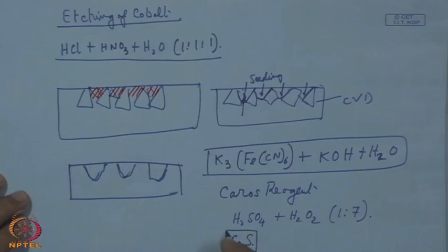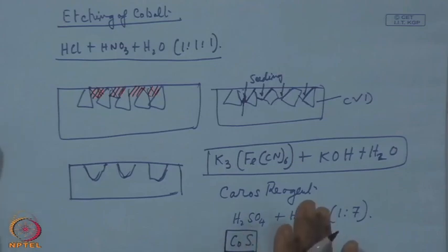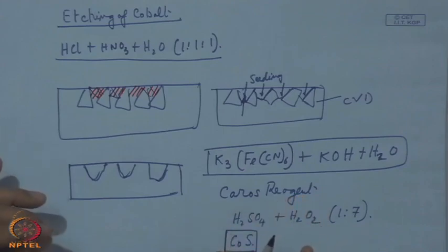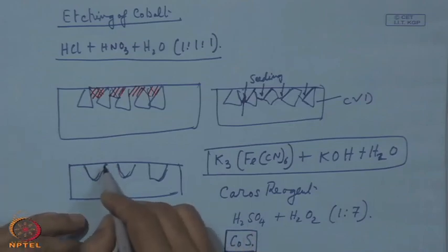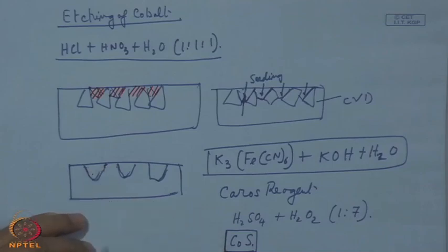So, the final aim in this etching process, which is a part of substrate preparation, is one of the very, very important steps in preparing the substrate for receiving that carbon in the form of diamond. So, this cobalt sulfide should form here in addition to the cavity formation. The part where originally cobalt is present should be transformed into cobalt sulfide, which is chemically extremely stable and also very, very passive.